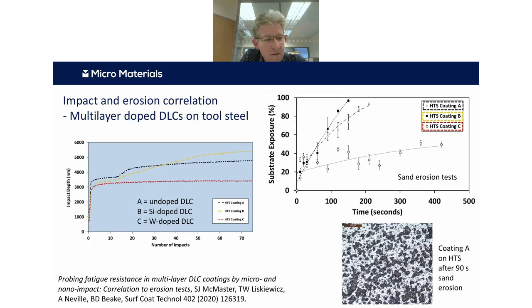And so Sam did those tests, but he also did some sand erosion tests, and these were individual tests. There's a certain amount of scatter because this is from a large number of tests, as you can see on the right. But nevertheless, you can see essentially the same trend, that coating C is much more resistant to erosion, and for the other 2 coatings you can reproduce the ranking, and also pick up that switch that happens between the 2.